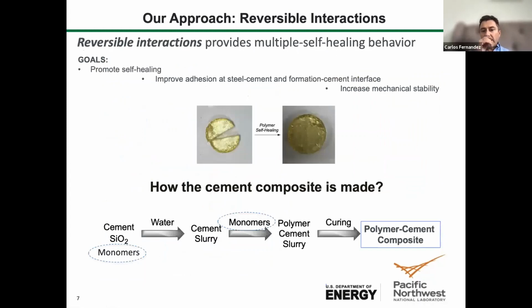So this is a thermoset epoxide, for example. Just at 70 Celsius, you can generate a fracture with a razor blade. And if you wait for a few hours at 60 Celsius, you will see that the fracture is completely healed. The tensile strength of this polymer is very close, if not almost the same as the original. And since the bonds in these polymers are reversible and dynamic, changing at a particular temperature, this self-healing can occur over and over again. How we introduce these polymers into the cement slurry.